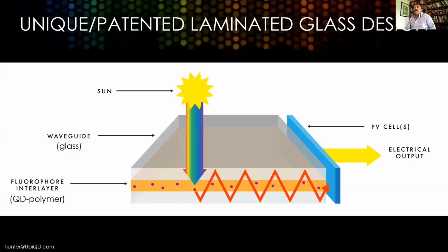So another thing to note that's different about our approach, in addition to the fact that we're using these unique quantum dots, is that we have a laminated glass solution. So in our market research, we've realized that glass is the only acceptable window material in the marketplace. And there's a number of reasons for that. But it probably isn't hard to agree with me just based on the fact that you don't see plastic windows. We can certainly make plexiglass at large scales, but it's not used in windows for a number of reasons. And similarly, coatings on glass are also not very common. You may have a window tint in your car that has a plastic coating, but very rarely would you find a plastic coating on a facade of a building.